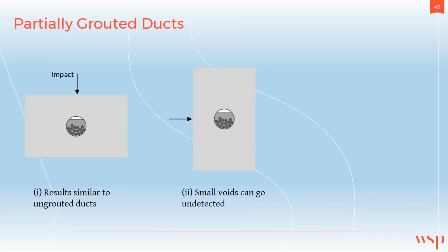Now, for partially grouted ducts, the response is going to be a little more complicated, and it depends on the location of the void with respect to the tendons and also with respect to the impact direction. For example, in the first case here on the left, the results that we get may look like as if this is an ungrouted duct, even if we have a really small void.